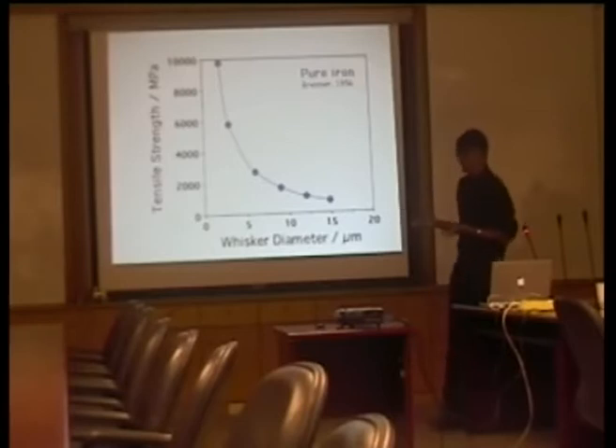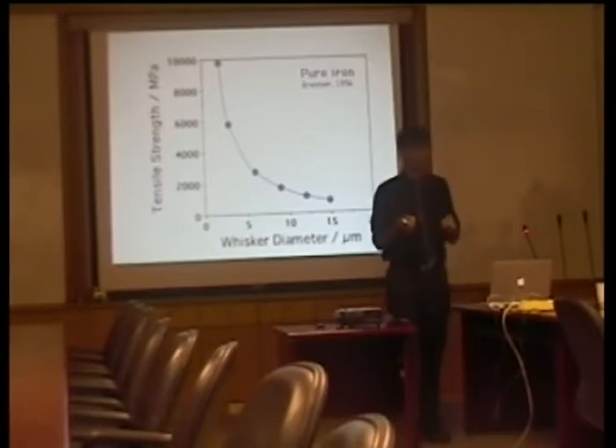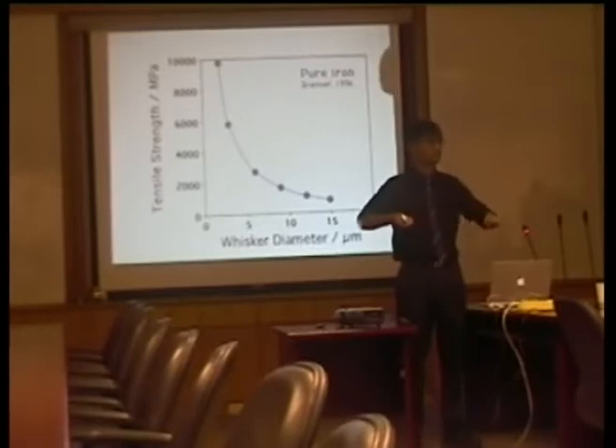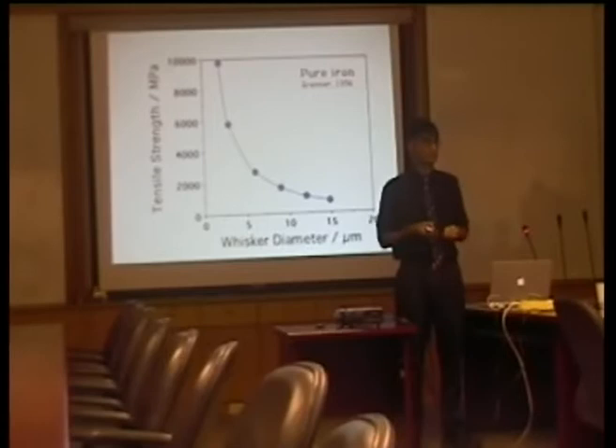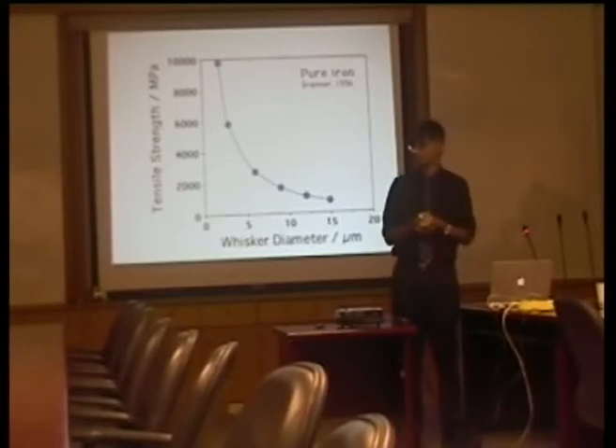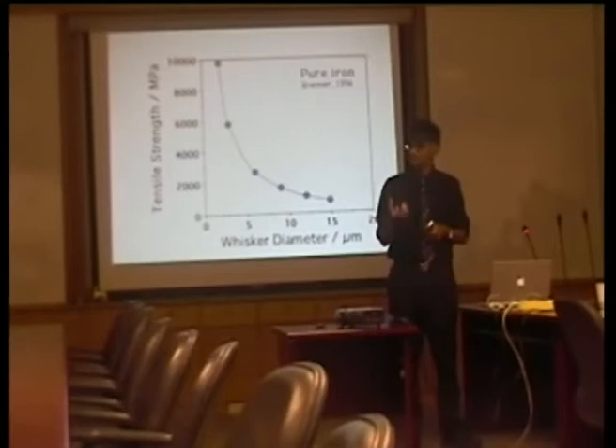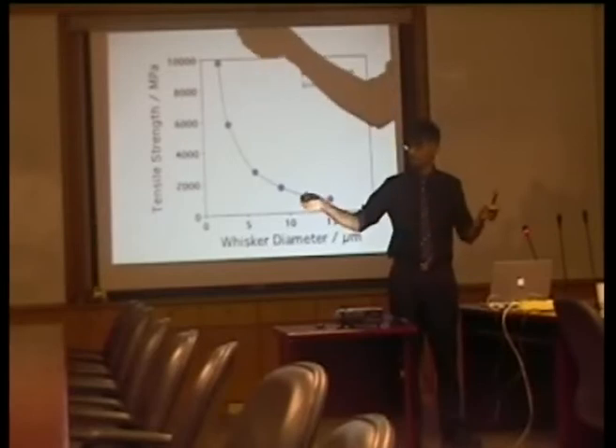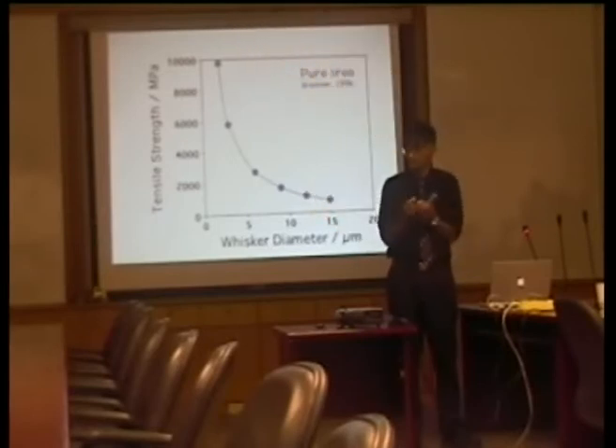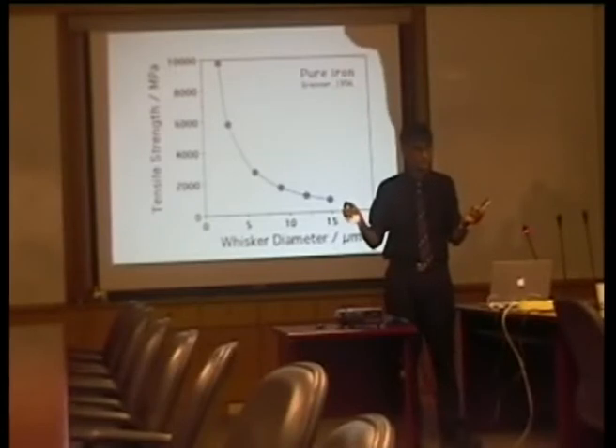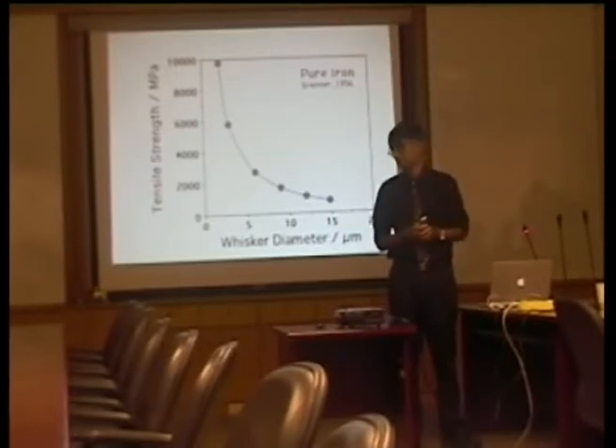So to achieve very high strength, you mustn't rely on perfection, because as soon as you make the material larger in size, the strength will collapse. The same applies to carbon nanotubes. They're very, very strong when they're of the order of nanometers in size. As soon as you make them 1 millimeter in size, their strength is much less than that of steel. And this is a fundamental science of scale. You will not be able to make a perfect carbon nanotube which is large. So you will never be able to exploit the strength of a very tiny carbon nanotube in a larger sample, because thermodynamics says you must have defects in your material.